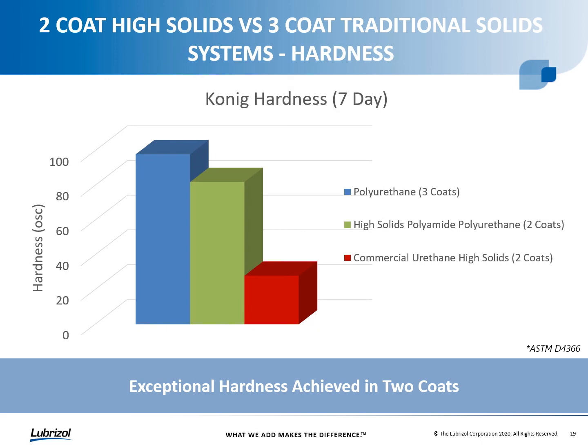I mentioned on the last slide, when we were looking at the Taber abrasion performance, that sometimes when you have materials that are hard or have high König values, they correspondingly have high Taber numbers or poor abrasion resistance. And what we see here in looking at 7-day König hardness, tested according to ASTM D4366, is that the high solids polyamide polyurethane, again comparing 2 coats to a 3-coat of the traditional polyurethane system, at just 2 coats has very good König hardness, upwards of 80 oscillations.